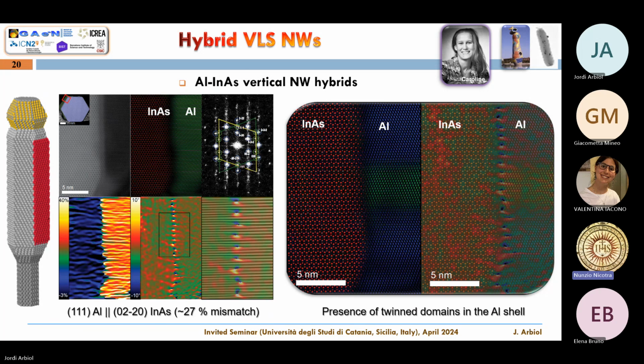And then you grow aluminum on top, covering some of the facets of the indium arsenide. Aluminum is a metal, but if you work at the millikelvin range, it can work as a superconductor. And it works. It's really nice. It works as a superconductor. But the problem is that we have many epitaxial problems here. Whenever you grow on top, this can be cubic or hexagonal, but at the end, you can attach the aluminum perfectly, but there are a lot of misfit dislocations at the interface. That is one point. Then you see that all the material grows perfectly, let's say, relaxed, which is okay.